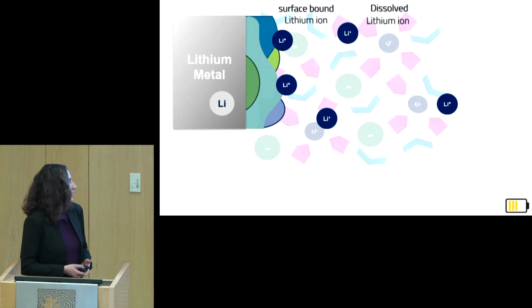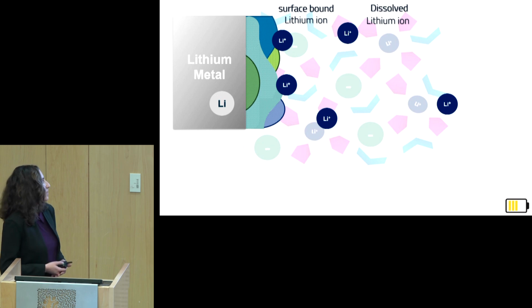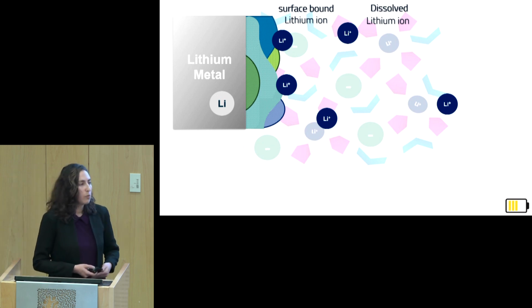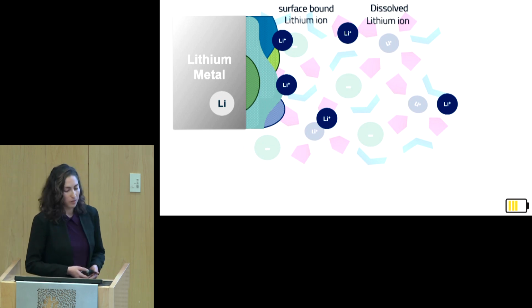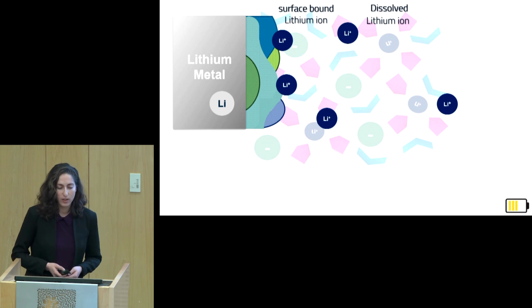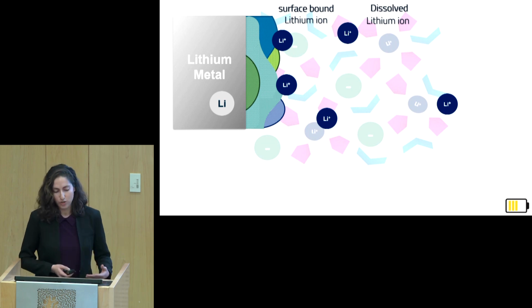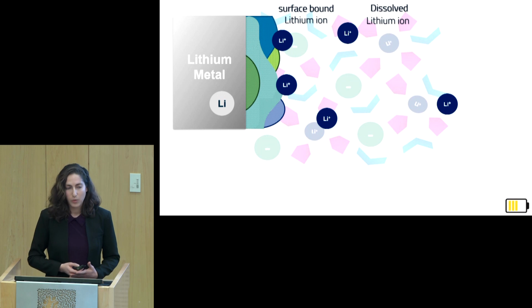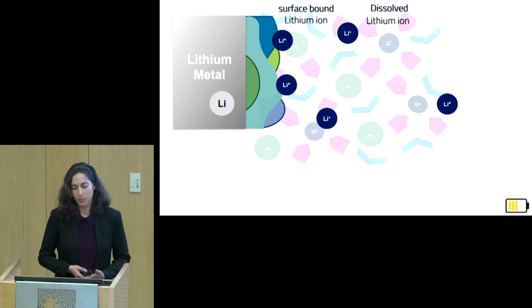So looking back at this scheme, this is a scheme of a half battery cell composed of electrolyte and only one of the electrodes, which is made of lithium metal. We can see again that the lithium belongs to three chemical environments: the dissolved lithium, the surface-bound lithium, and the lithium in the electrode, the solid lithium. So we expect to see three peaks in the NMR spectrum.